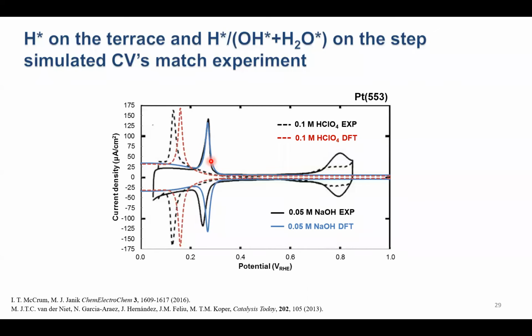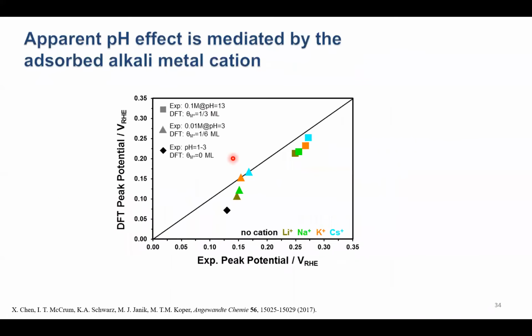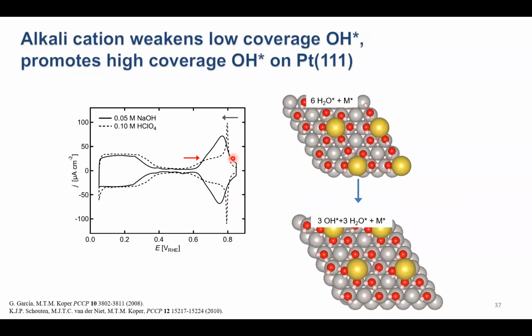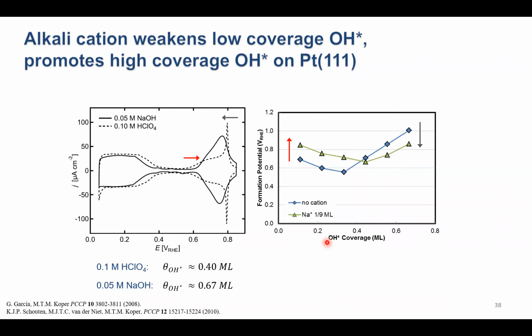And so the cation weakens low coverage adsorption. That's why the peak shifts, and it can also slightly promote high coverage hydroxide adsorption. We can model this on the flat platinum-111 surface, just like we did on the step sites, and we find roughly the same picture: the presence of the cation weakens low coverage adsorption. The blue points are the OH adsorption potential as a function of OH coverage without a cation, and with a sodium cation, we see that it weakens low coverage adsorption and strengthens high coverage adsorption.